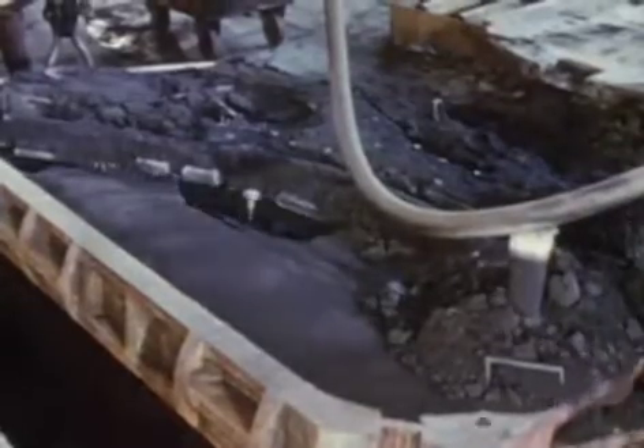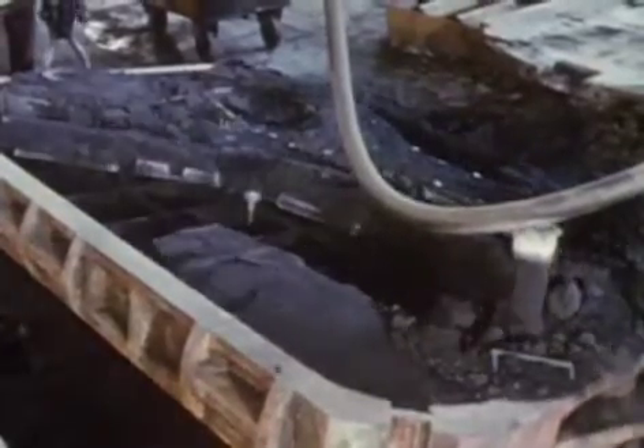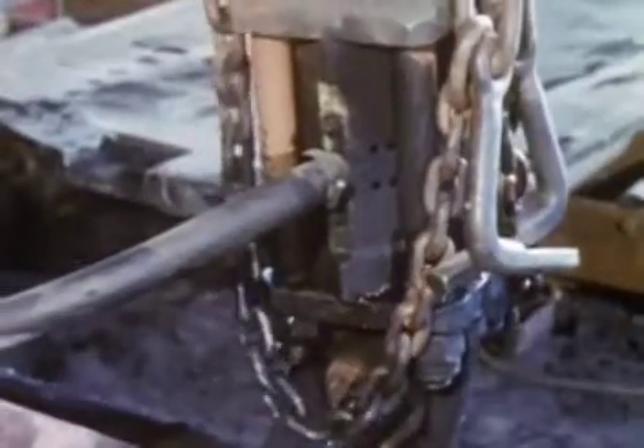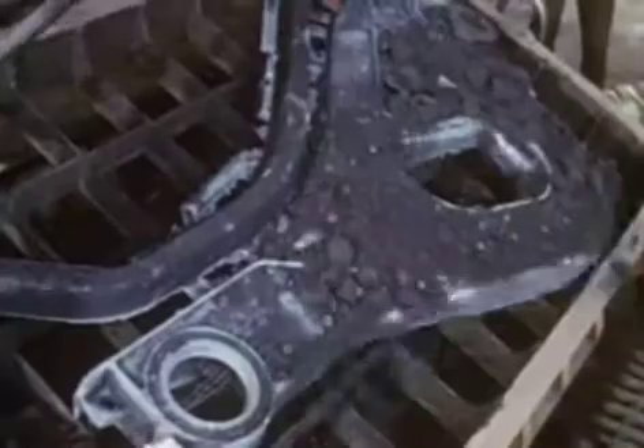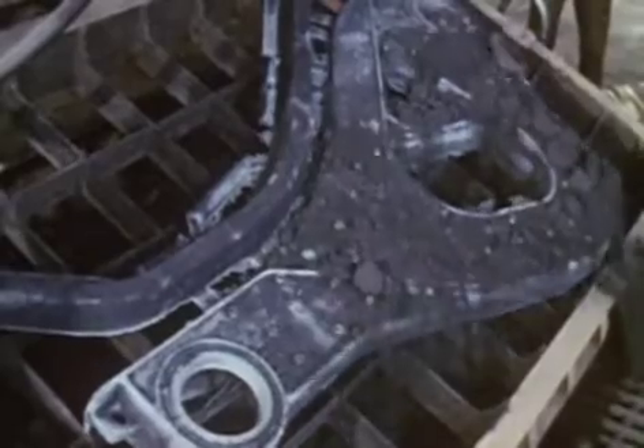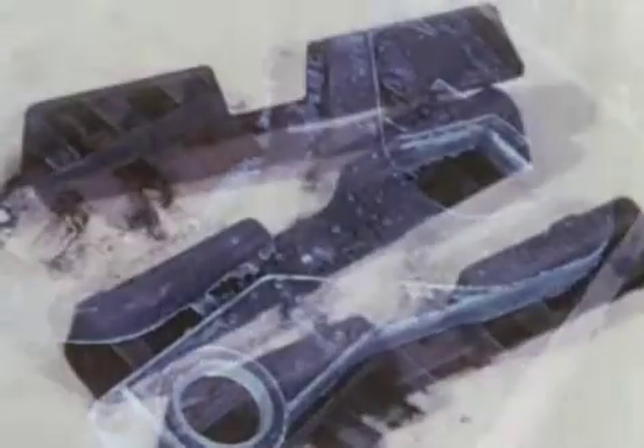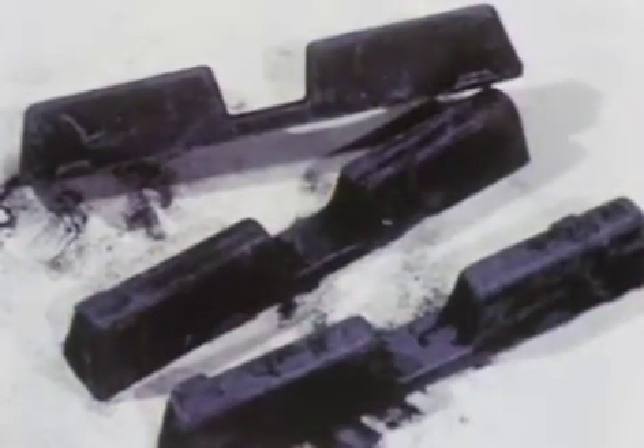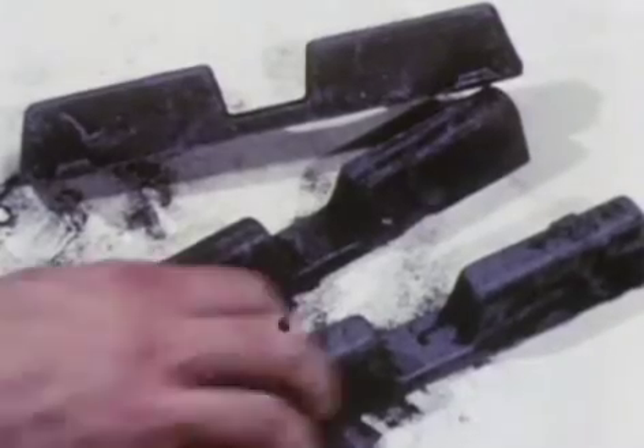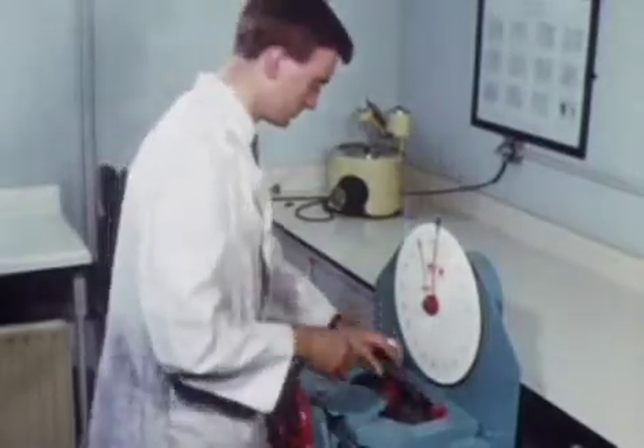When fully cooled, the casting is shaken out of the mold, and the 3 test pieces which were poured at the same time and under the same conditions as the boiler section are sent to the laboratory for a bending test to establish the ductility of the metal before the casting leaves the foundry.